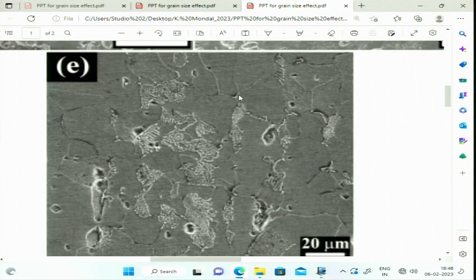So, these are actually forming along the ferrite-ferrite grain interface, that means the ferrite grain boundary, whereas if you consider this particular one, you follow the cursor, here it is falling at the perlite-ferrite interface. So, that means the perlite colony and ferrite grain interface is forming. For example, here the three pits are actually along the ferrite grain. So, every time we are seeing some of the pits, they are actually forming along the grain boundaries, whether it is an interface between perlite colony and ferrite grain or between ferrite and ferrite grain.